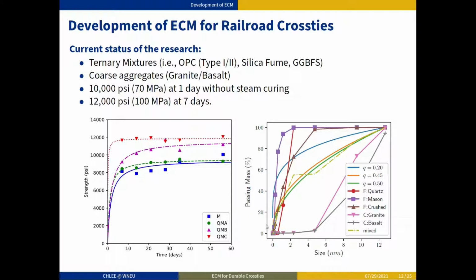Of course, we still have room to improve to higher strength rather than what we are showing over here. Another thing that we would like to highlight here is that the mixture proportion used for this particular concrete is not really different from the conventional concrete. What we did was we carefully selected coarse aggregates, which is a mixture of granite and basalt, and we carefully chose the size distribution of a mixture of fine and coarse aggregates according to the designated size distributions.